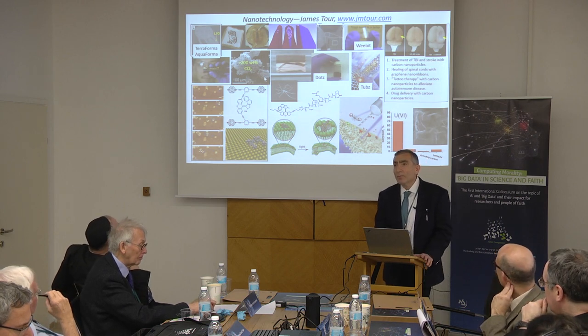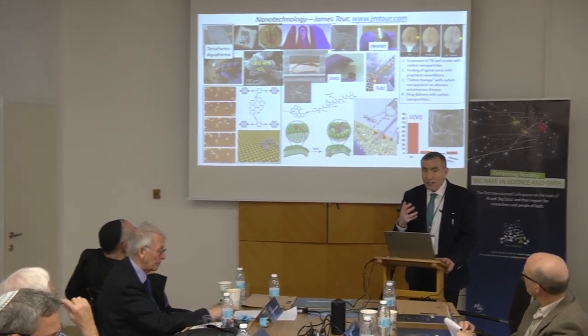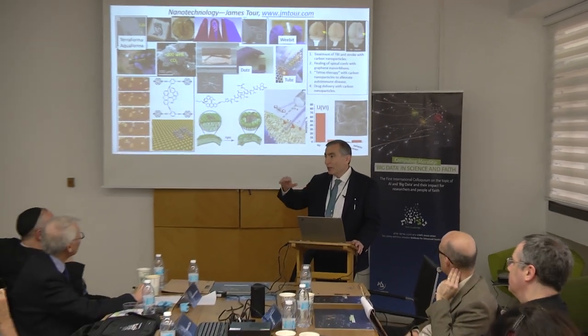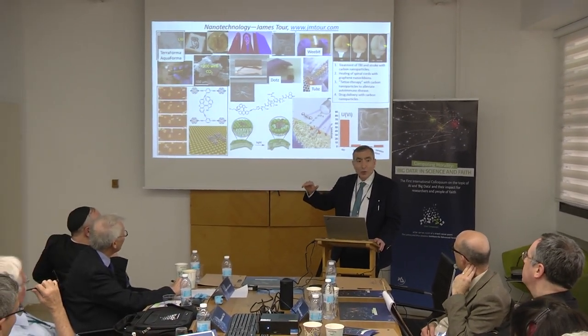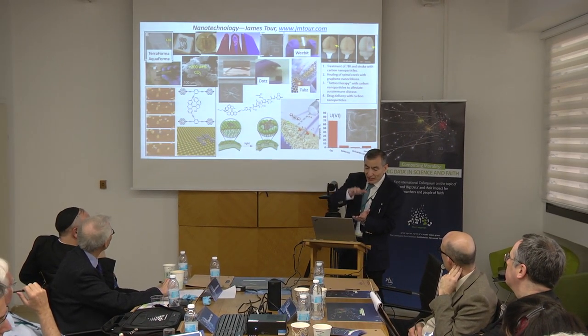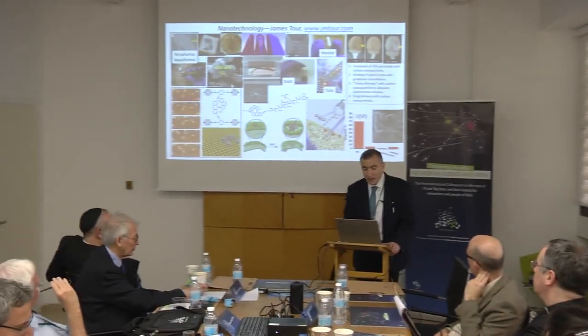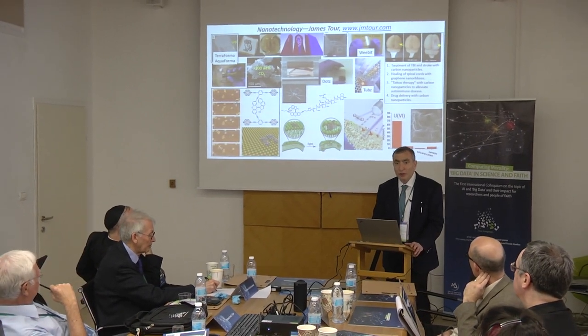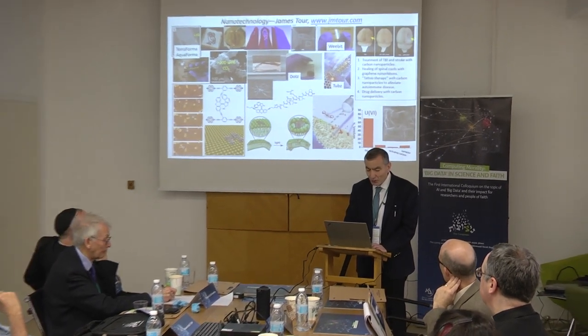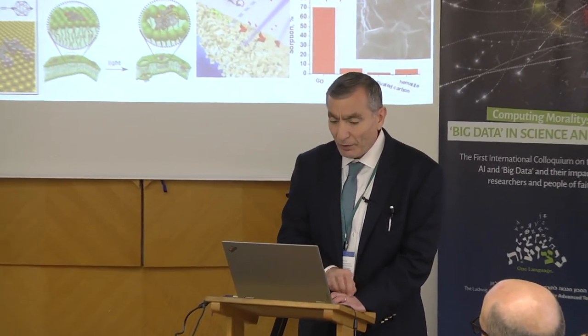We found a way to convert asphalt — the material that roads are made out of — to a highly porous carbon material with 4,200 meters squared per gram. A sheet of graphene has 2,800 meters squared per gram, but we get 4,200 because we have nanopores that open up and you can stack molecules within them. We can trap over 200 weight percent CO2. This is a very inexpensive material, and it's reversible just based on the pressure swing reaction. This has been licensed by Apache, a big U.S. oil company, for utilization on all of their oil field platforms.